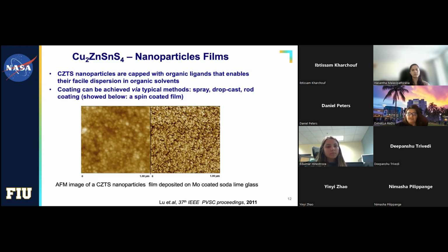What that does is that when we want to melt these things, the melting point of a material, for example the CZTS material, in bulk, if I have a big chunk of this crystal and I want to melt it, it will take 1,000 degrees Celsius to melt. Well, guess what? When I operate at the nanoscale, these nanoparticles are going to melt at 350 to 400 degrees Celsius. Well, that's amazing that I can do that on a bench top,